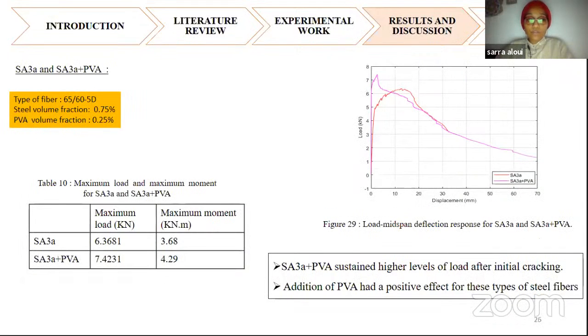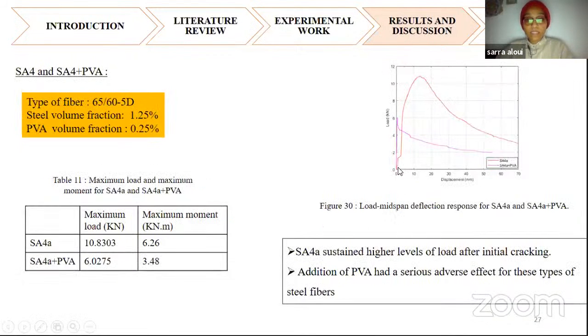For the third one, the specimen with PVA has a higher maximum load. We can say that the addition of PVA has a positive effect. For the fourth one, that contains more steel fibers, here we can say the addition of PVA has had a serious adverse effect. So the addition of PVA is not a positive addition for this specimen.